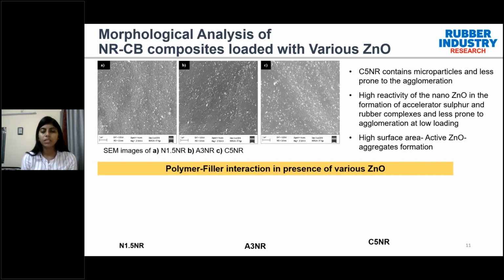So the influence of these properties we are trying to interpret with the polymer filler interaction by using morphological analysis such as SEM and AFM. From the SEM analysis, we can see that the compound with the conventional zinc oxide, which has micro zinc oxide particles, is less prone to agglomeration, and the nano zinc oxide, having high reactivity and higher surface area, shows agglomeration at higher loading. But even though we added it at 1.5 pHr, the lower loading, the agglomeration tendency was very low.